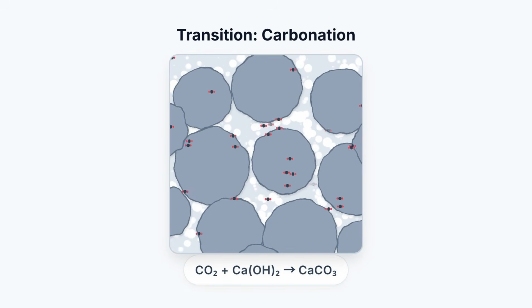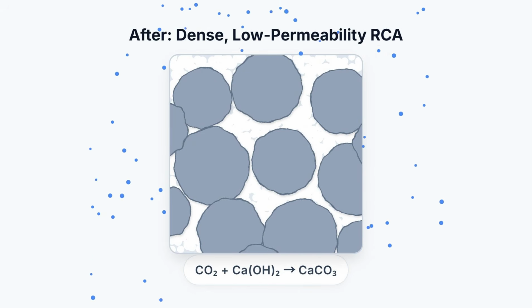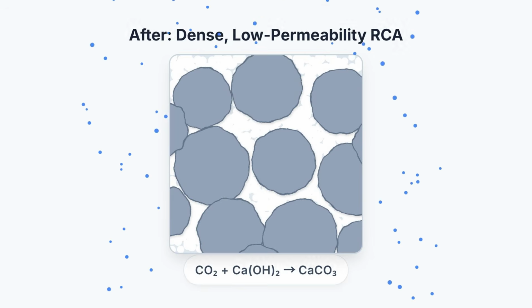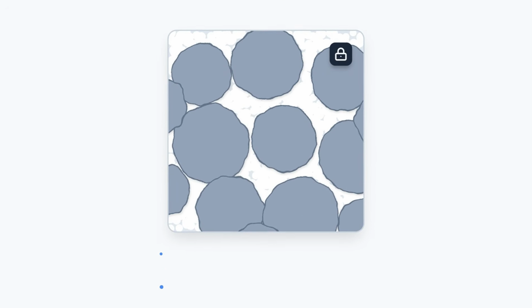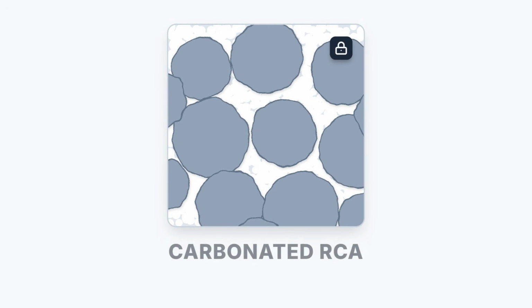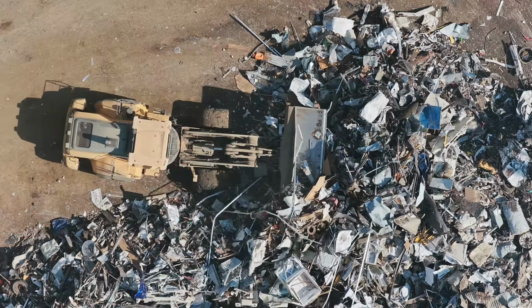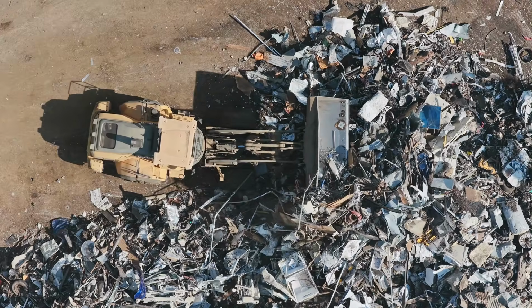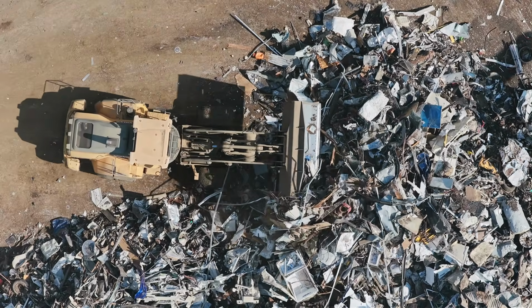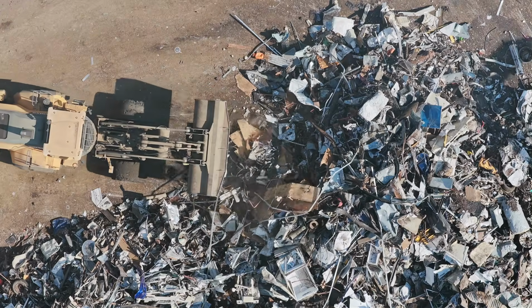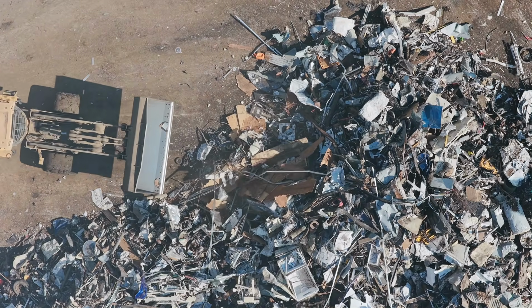Instead of the gas escaping back into the air, it gets trapped and turned into solid minerals inside the recycled concrete aggregate. This makes the surface stronger, keeps water out, and results in what we call carbonated RCA. So this is not 2 separate ideas. It is one simple loop. Recover the RCA, cure it with carbon dioxide, then reuse it in new concrete.